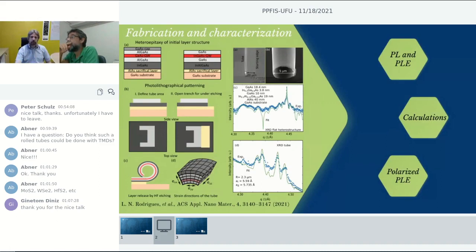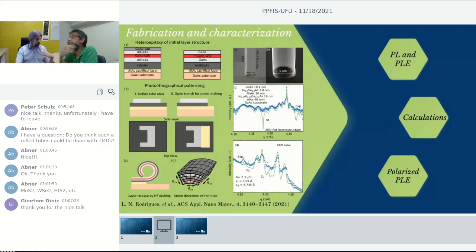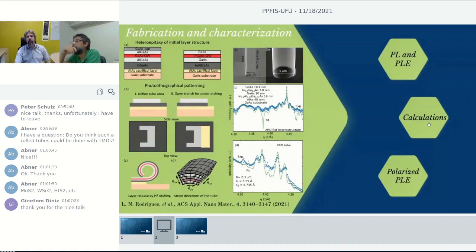The samples look like this: you have the starting edge, the film that rolled up, and the tube line parallel to the starting edge, with a diameter of about 5 micrometers and a wall thickness in the range of about 60 nanometers. Since we do epitaxy, we have complete control over the strain state. We use high-resolution XRD to determine the initial strain state, then go to the synchrotron to do diffraction on the tubes to determine the strain state of the tubes themselves. With this knowledge, we can feed it back into calculations to understand what's going on.